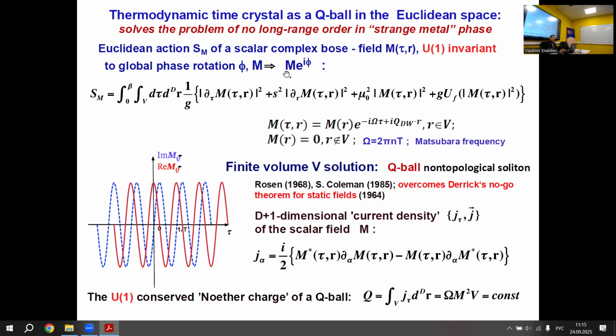So then it was proposed that if you consider this phase shift as Matsubara time dependent with some particular frequency, but the frequency could be only a boson Matsubara frequency because this is Euclidean action. So T is temperature, 2 pi n, where n should be an integer. And if you consider this field having this Matsubara time-dependent phase shift, then it proves that Derrick's theorem could be violated, and a finite size solution that minimizes this Euclidean action and looks like a finite size soliton exists.